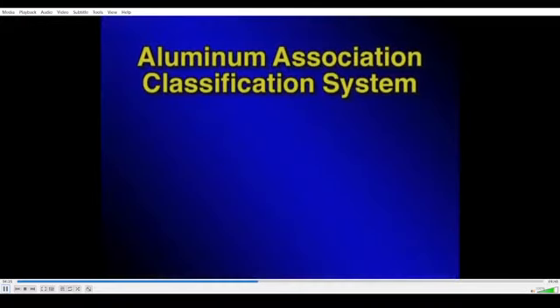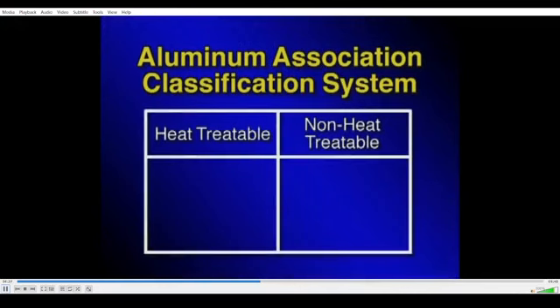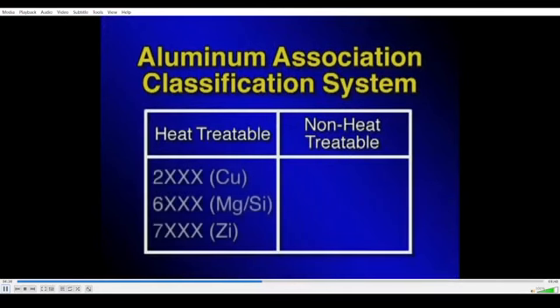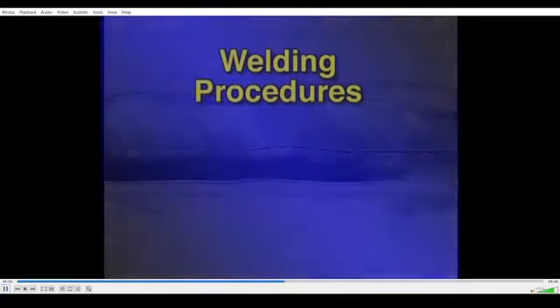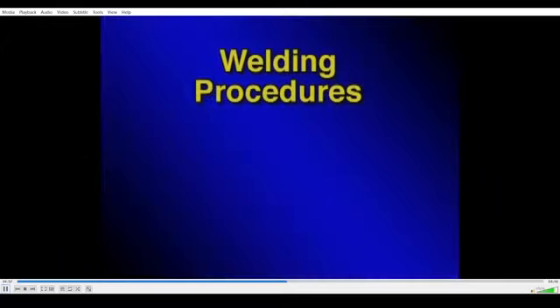Each type of aluminum falls into one of 2 categories, heat-treatable or non-heat-treatable. The heat-treatable alloys include the 2, 6, and 7000 series. These alloys acquire their strength from heat treatment. They'll crack if you try to weld them without filler metal. And heat-treatable alloys above 7039 are not recommended for welding at all. Also, high heat input and the use of preheat will cause loss of strength and cracking in the fusion zone along the toes of the weld. Typical procedures for welding the heat-treatable aluminum alloys involve the use of filler to prevent cracking.